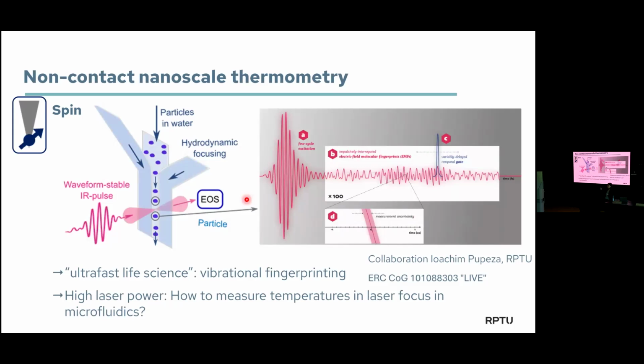So you're not sticking a thermometer into your 1 micron microfluidics channel, right? It's not working. So here we also need a non-contact thermometry. And at the moment we are trying also to use the NV centers here as thermometers, because they are even using windows of diamond for the microfluidics. So it could even be that we could nicely combine this here. They're in principle using the diamond for the high transparency, but it could be a nice combination.